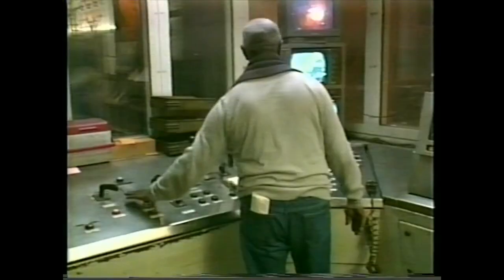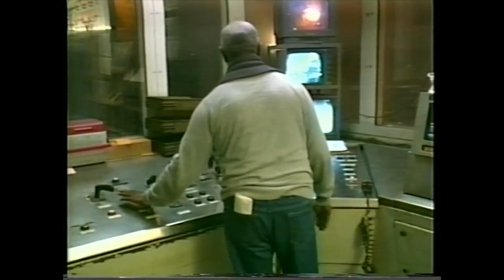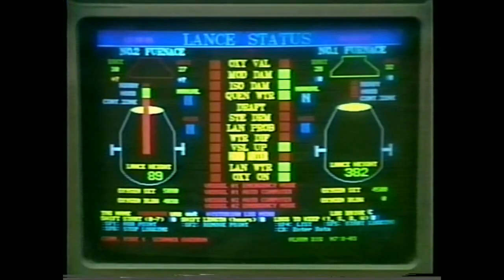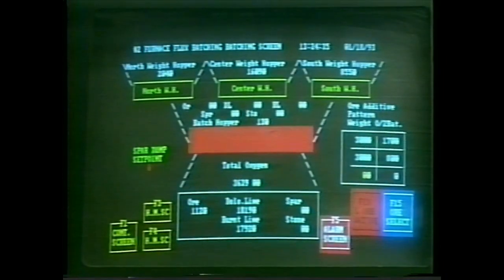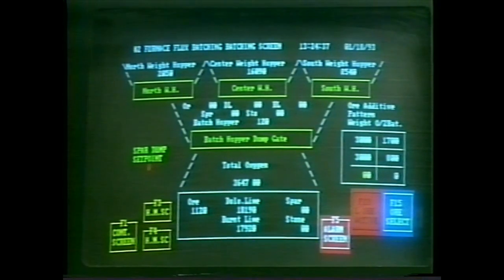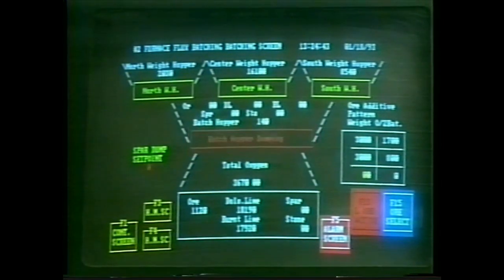The pulpit operator now initiates the oxygen blow. The amount and rate of oxygen and the lance height patterns for the blow are determined by the process computer. After the oxygen is turned on, the computer activates the flux batching system. This system discharges the correct amount of fluxes into the furnace at the proper time.